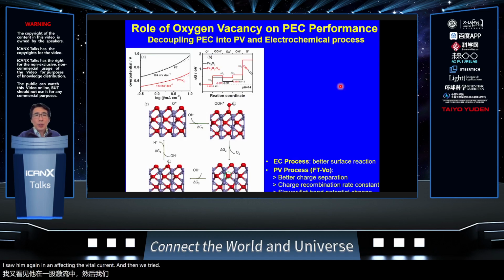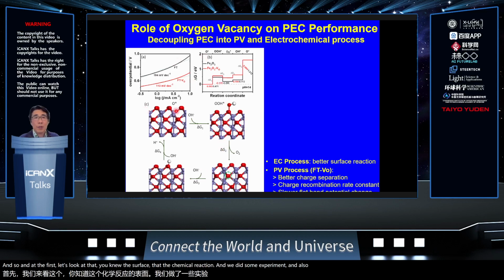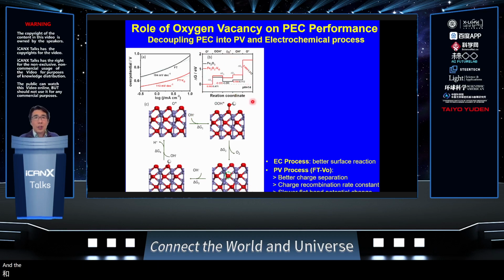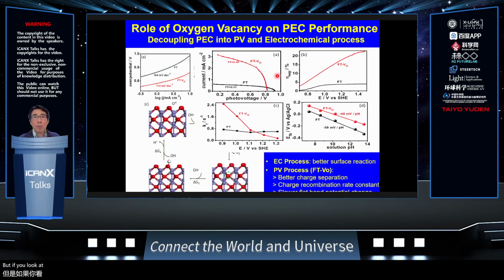And then we try to decouple this into the PV and the EC system. First, let's look at the surface electrochemical reaction. We did some experiments and also calculation and simulation work. We found that after we induce the oxygen vacancy, the surface oxidation reaction, the oxygen evolution process, can be accelerated. That means oxygen vacancy is good for the surface reaction. But if you look at the PV effect, between the bulk and the interface, and between the solid and the electrolyte, it's much more complex.